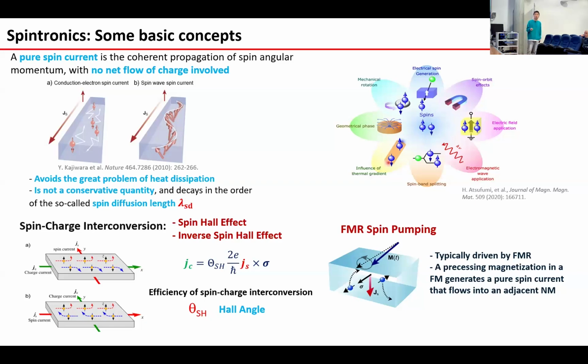This process can be achieved by the spin Hall effect and inverse spin Hall effect. As shown in this figure, with the spin Hall effect you achieve charge to spin conversion: applying a longitudinal charge current in this direction, the spin-up and spin-down charges separate in opposite directions, generating a pure spin current. While the inverse spin Hall effect is the contrary phenomenon: once you inject a spin current along this direction, the charge accumulates along one direction, generating an electric field and a charge current. This spin to charge conversion can be expressed by this expression, and here the spin Hall angle is a quite important parameter, an indicator of the efficiency of the spin to charge conversion.